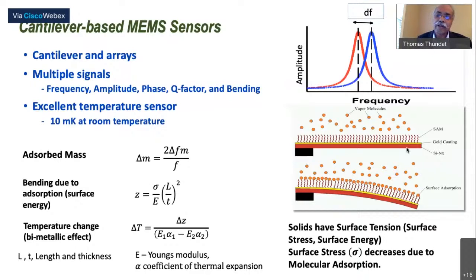And molecular adsorption always involves energy minimization, surface free energy changes. So that changes a differential stress on the top and the bottom, and the cantilever undergoes some kind of bending, and we can measure that very precisely using either piezo-resistive detection, or we can use optical beam deflection. And that's what's shown here. Basically, surface stress and the bending are connected. Change in surface stress will result in change in length, change in the bending.